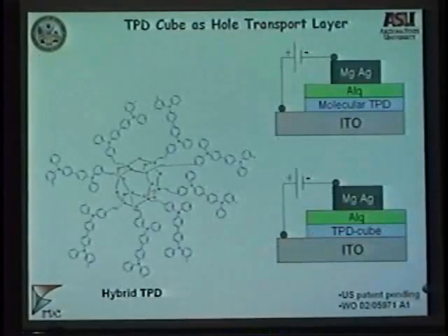And this is what we made for comparison. We made the device on indium tin oxide. The TPD cube, as we call it, was dissolved in chloroform and then spin coated. Then we took the pure form of TPD molecular material and evaporated it to the same thickness.